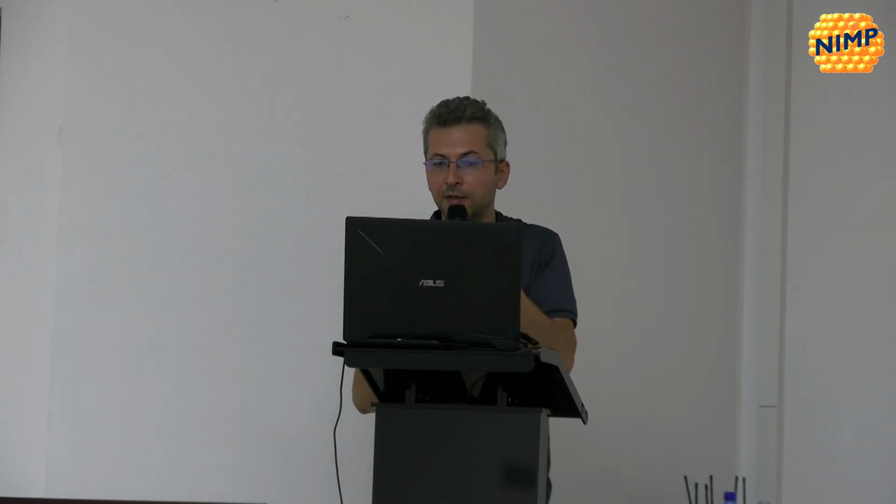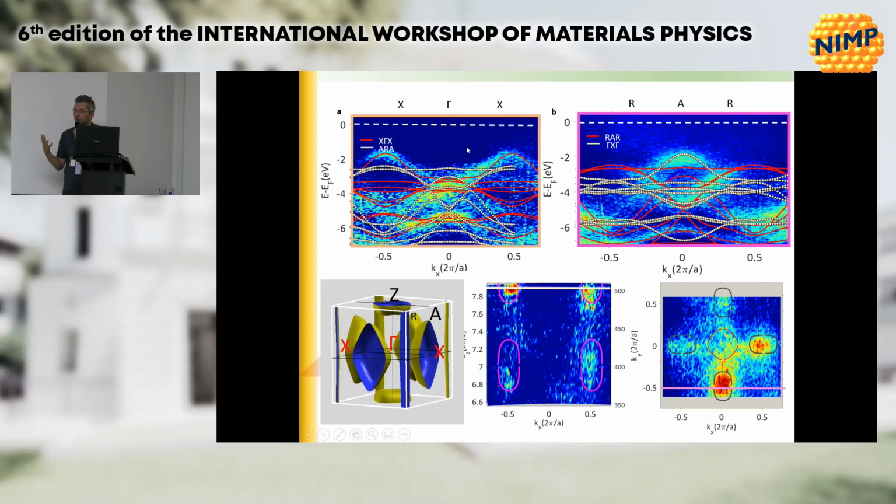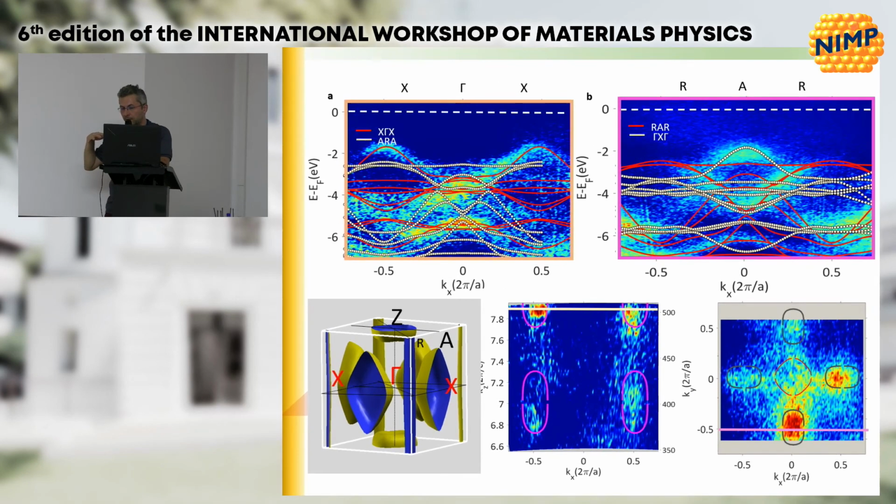Looking here in the band structure, not seeing any impurity level, any electron or hole related state, the only thing we may infer is that if they exist, they are above the Fermi level, and in photoemission we see only the occupied levels, or they are incoherent. They don't have a well-defined energy. Okay.